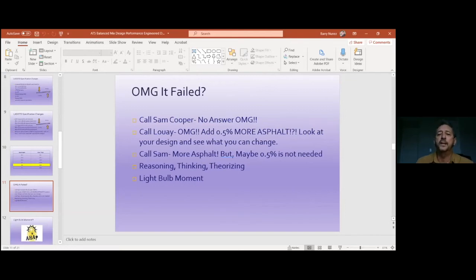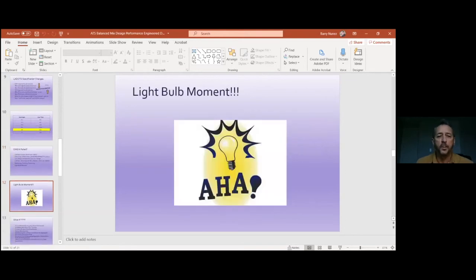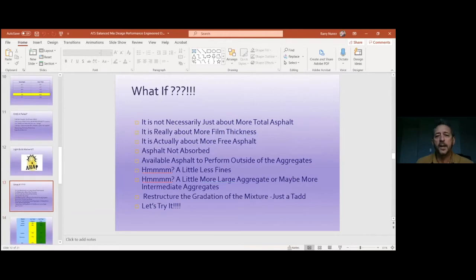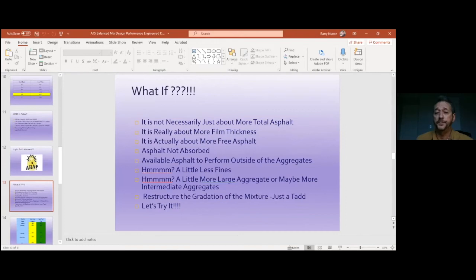So we start reasoning and we start thinking and we start theorizing. And then all of a sudden we had the light bulb moment. We thought about it and we said, okay, so it's not necessarily about a total more asphalt. Maybe it's really about more film thickness. Maybe we don't have a spec on film thickness, at least not in dense graded mixes, only in an OGFC, open graded. So it's actually about more free asphalt, maybe. You know, maybe about the asphalt that's not absorbed, the asphalt that's available to perform outside of the aggregate.